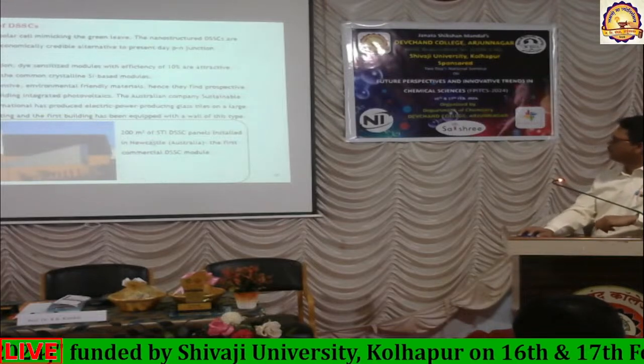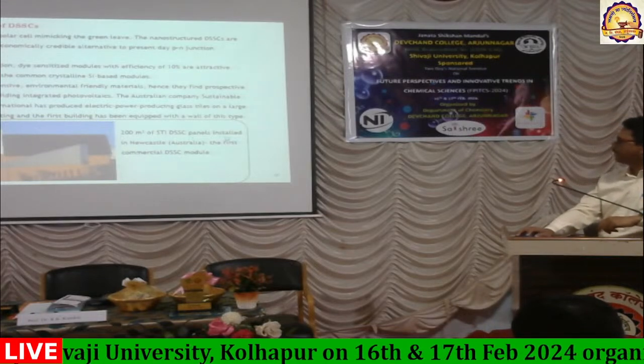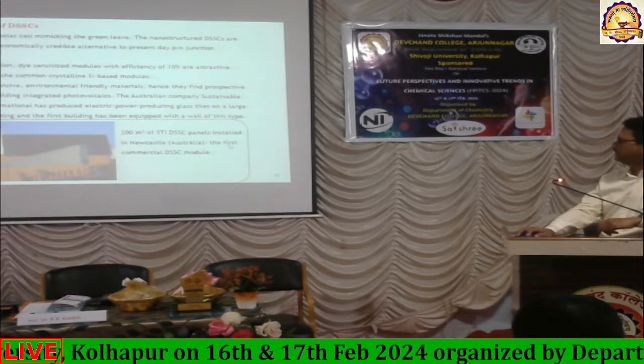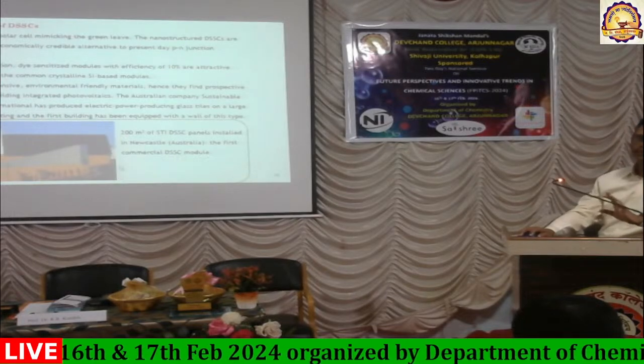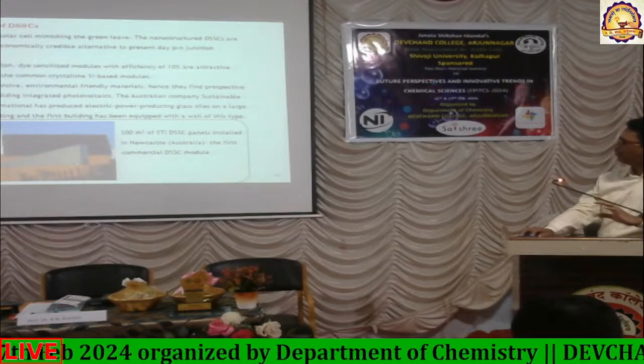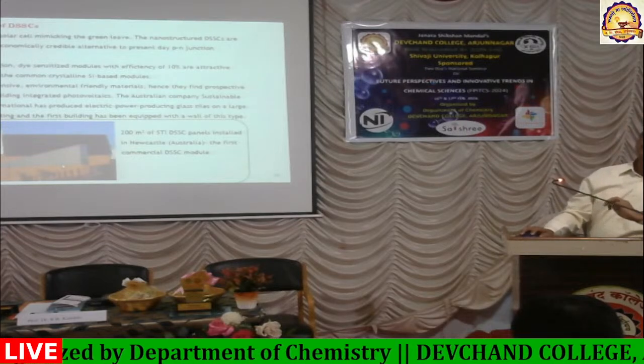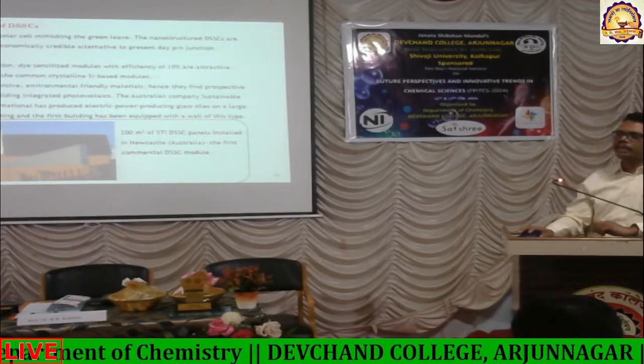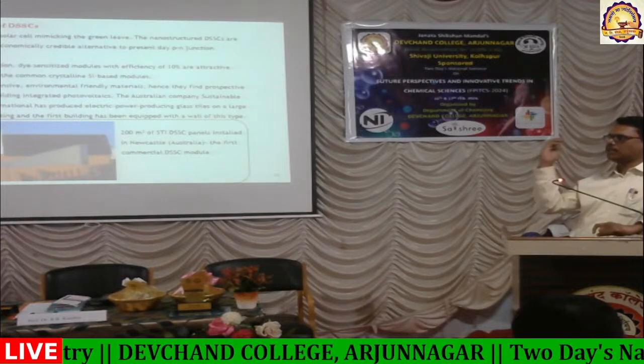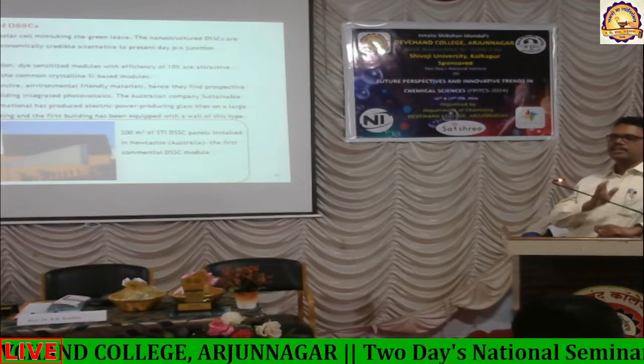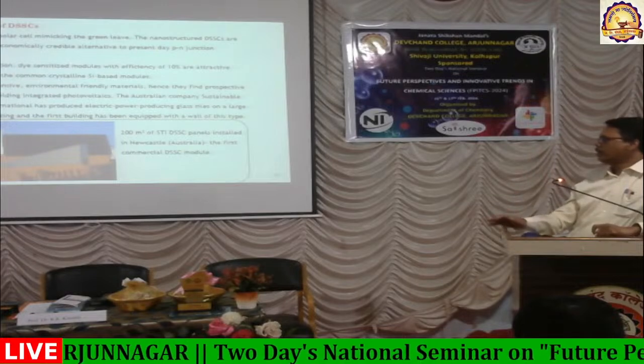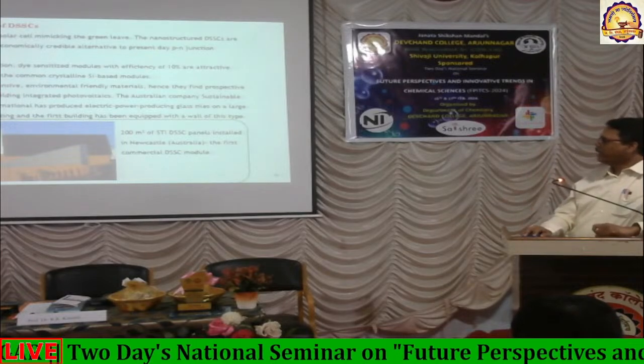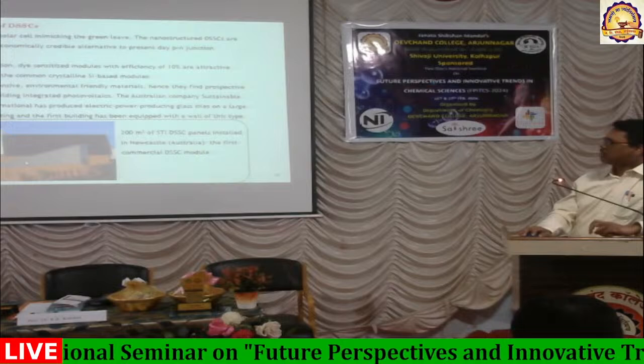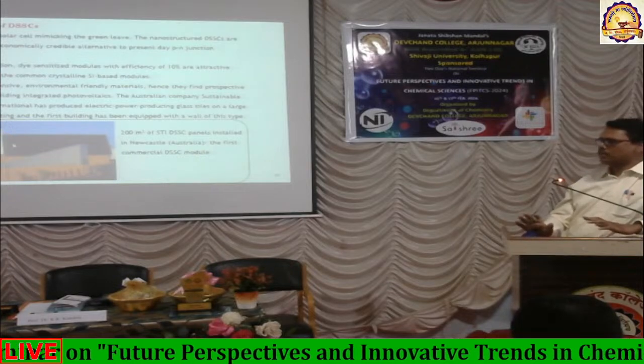So this is a 100 square meter STI DSSC panel which is installed in Newcastle in Australia, the first commercial DSC module, where these are the organic molecules, because earlier the efficiency was good with the ruthenium dyes. Silicon, of course, people are still using silicon, the efficiency is really good, and lifetime is also good with silicon, and it's available, but the cost of production of silicon is more.